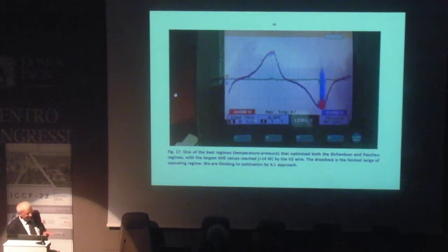The third one is the best regime, and it really works better. This is the regime that gives the most advantage. In this measurement, we have the largest signal, stable over time, days working, 40 watts. These high frequency components are very, very difficult to identify, and are the key point. 5 minutes, okay, sure. This is the key. We need this kind of regime. So more or less it is at the minimum of the Paschen curve.